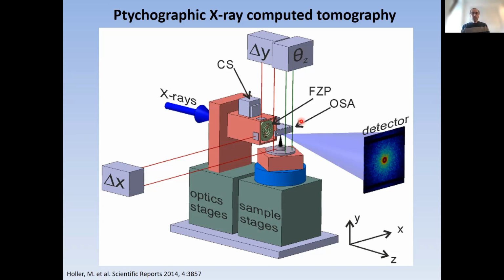And just to talk briefly about what it is, it's a form of imaging technique using X-rays. So in a way, you can think of it as analogous to X-ray tomography. We have a sample, we fire a beam of X-rays at it. We have to do that in a synchrotron. But instead of getting an image like you do in X-ray tomography, or even if you make an analogy to TEM tomography, what you get is a coherent diffraction pattern of the image. What we do is raster the sample with the beam to collect overlapping diffraction patterns. And then, of course, we rotate the sample to do that in 3D. So it's a process that actually takes several hours to acquire a data set. And then through some black magic algorithm that I won't pretend that I completely understand, we can reconstruct what the sample looks like.